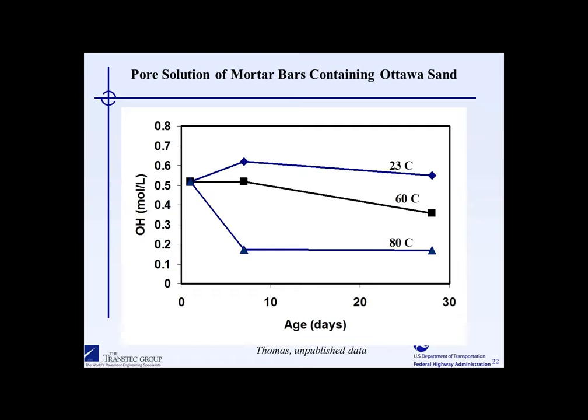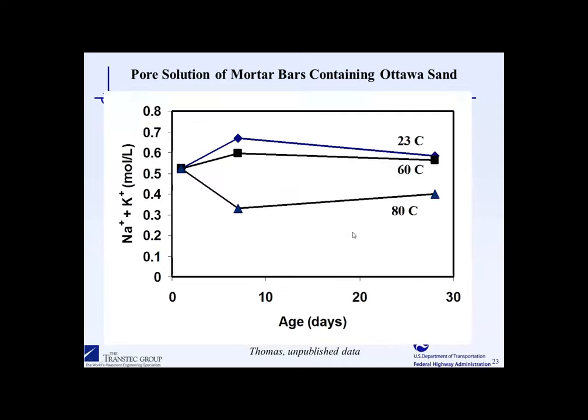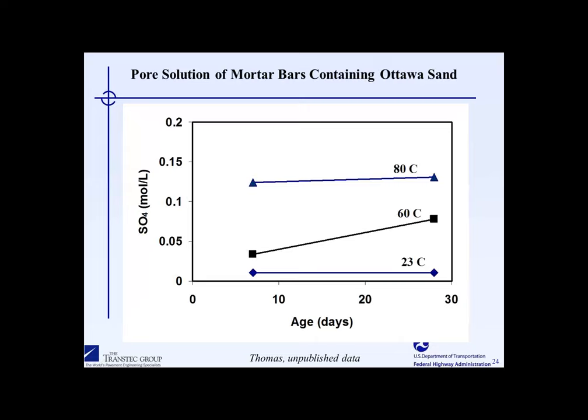What you'll see here in the first slide is the most important point. On the y-axis is the hydroxyl concentration, which is a direct indicator of the pH. As we go from low temperature testing all the way to, say, 60 or 80 degrees Celsius testing, our pH drops off considerably, given that the hydroxyl content is decreasing. The effect is obvious at 60 degrees and even more so at 80 degrees Celsius. If we look at the alkalis in the bars, they are reduced, but at nowhere near as much as the hydroxyl concentration. We always have to have balance between the positively charged sodium and potassium and the negatively charged ions, which are typically just hydroxyl. But what you'll see in the next slide is what's coming into solution at 60 and 80 degrees Celsius: sulfates are actually going into our solution. And that was the reason why we saw the drop in the pH two slides ago.